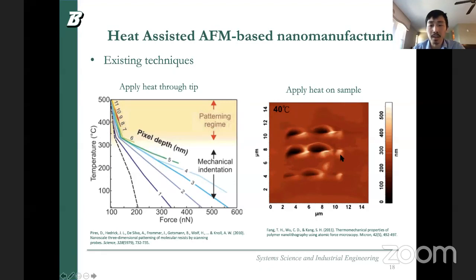Besides that, there's another technique applying heat on the sample. On the sample, it shows only 40 degrees C. We can do some nanomachining on it with only about 50 nanonewton. This is a paper published in Micron. However, we can barely see any patterns, because of the substrate temperature increase and certain limitations, so it has not-so-good quality.